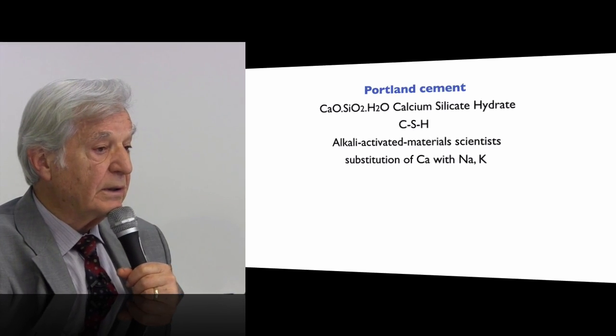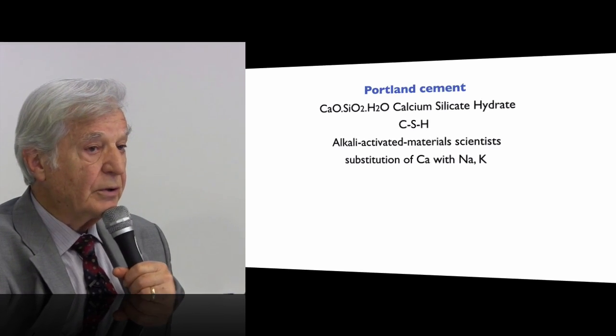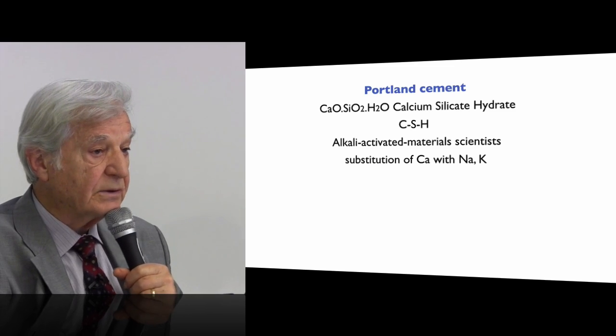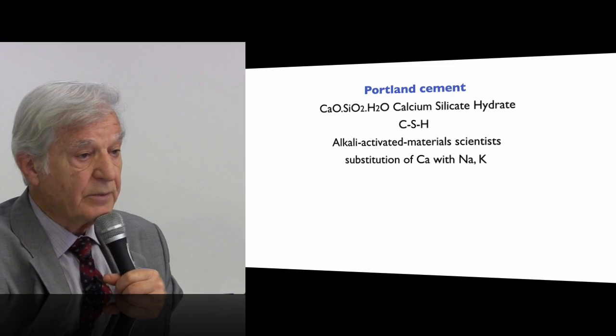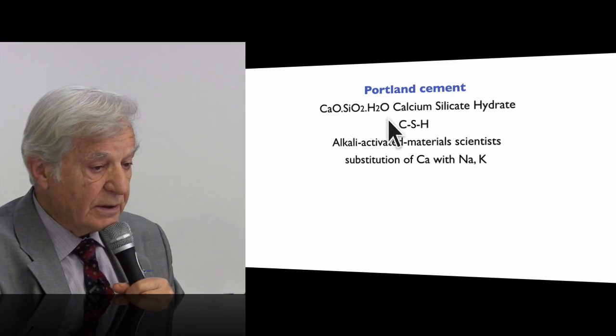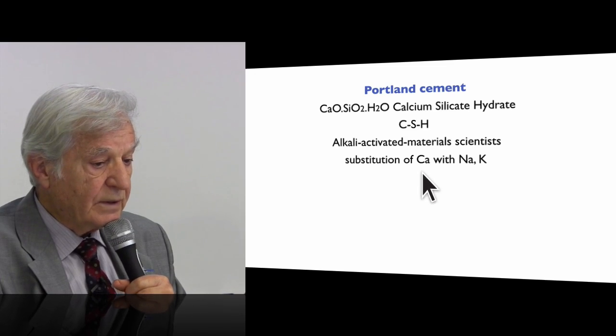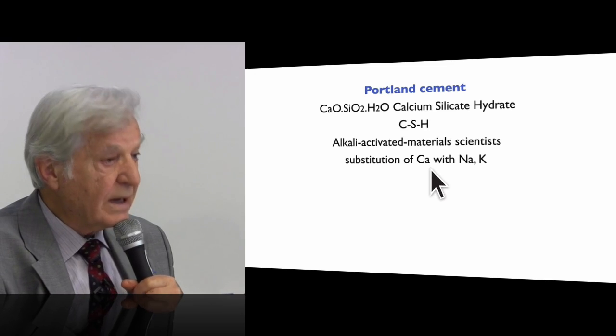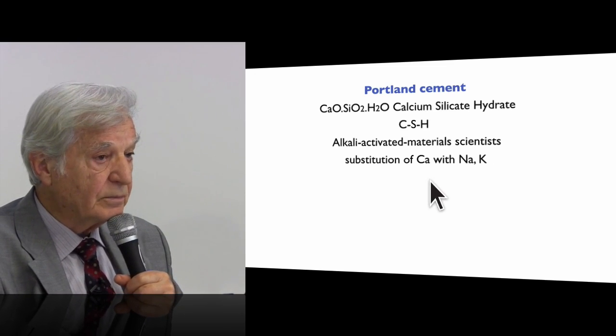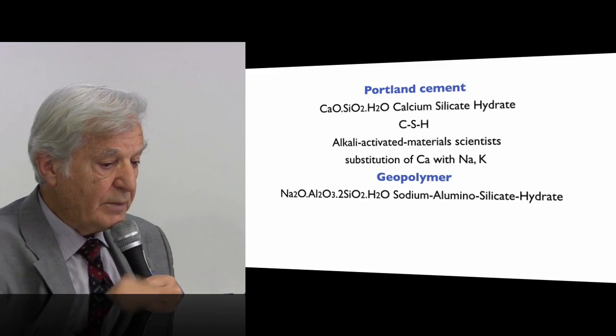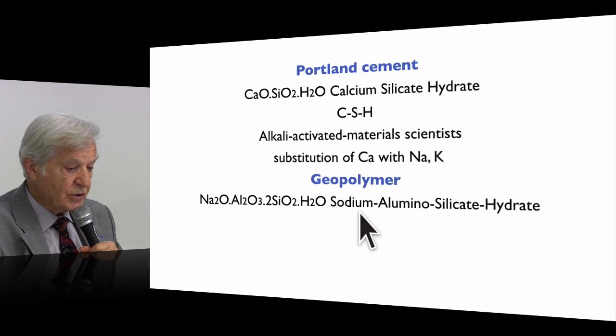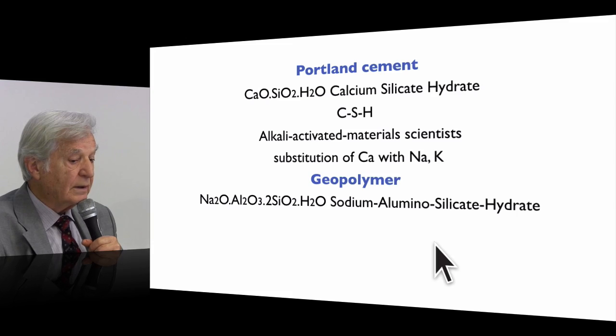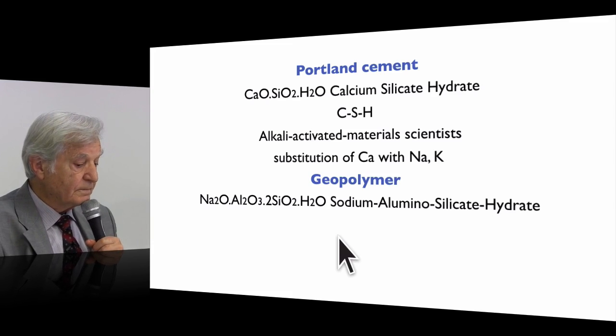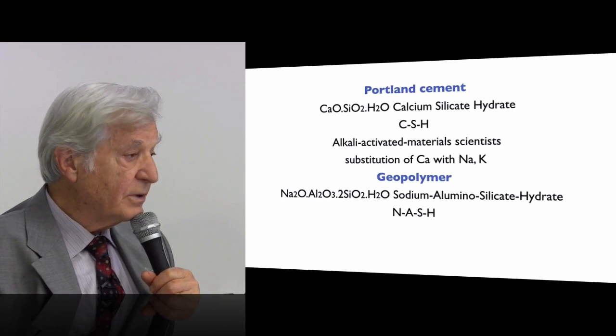Calcium is known to be insoluble in water. So you may have a calcium silicate hydrate. You don't care about the water, the calcium still remains in place. And you may use this terminology. But if you replace the calcium with the sodium and the potassium, as they are doing for geopolymer, sodium, aluminum, silicon oxide, sodium aluminosilicate hydrate, the sodium is very soluble in water. That means if it is a hydrate, all the sodium will be leached out, will move. So they call it NASH, which is totally wrong.